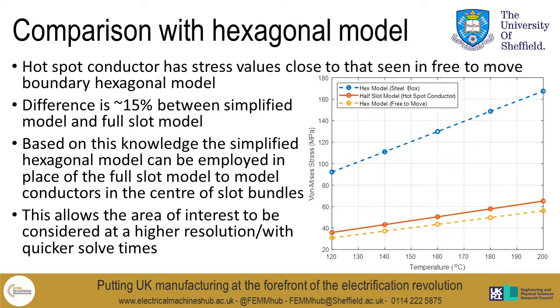So this slide shows a comparison between the peak stress values which were observed in the hexagonal models and the half slot model that I've just been discussing. What you can see from this is that the results which were obtained for the half slot model are quite close to the free to move case. In this instance, the difference is of the order of about 15% between the simplified hexagonal model and the full slot. Based on this knowledge, it's possible for us to use the hexagonal model in place of the full slot model to model conductors in the centre of the slot bundle. This allows the area of interest to be considered at a much higher resolution and or with quicker solving times, which is a useful finding.